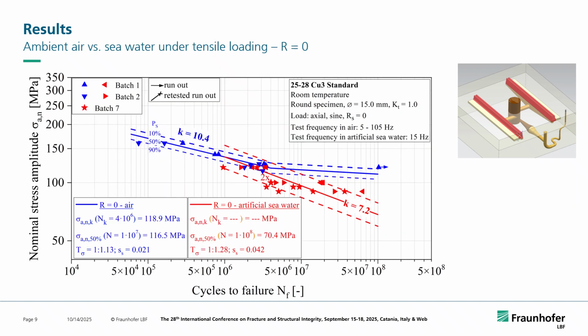Now looking at the comparison of ambient air and seawater under tensile loading, we have here the results for the batch 1 and 2 that we investigated. What is not untypical under corrosion is that we follow more or less the slope. We get a bit steeper slope, but we definitely have no knee point here, and it goes down straight on with an even steeper slope than for the test under ambient air without pre-corrosion, and 10.4 is the value for the ambient air results.